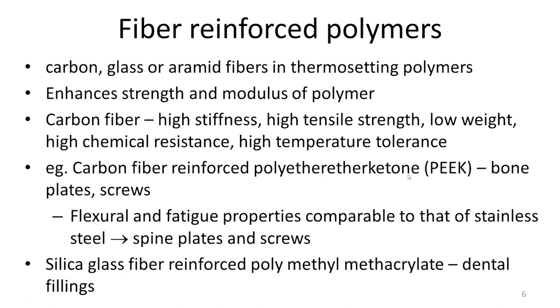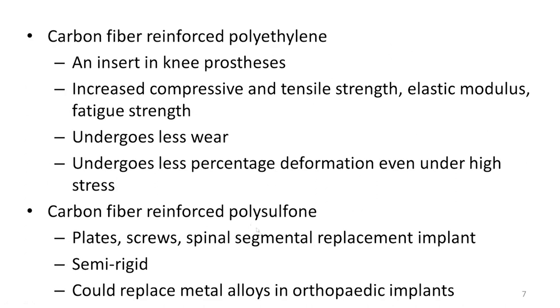Carbon reinforced polyether ether ketone is used for bone plate screws, with flexural and fatigue properties comparable to stainless steel, and is also used in spine plates and screws — while being much lighter. Silica glass fiber reinforced PMMA is used in dental fillings, where the fiber gives toughness. Carbon reinforced polyethylene is used in knee prostheses, where there is a lot of attrition, bending, and flexural stress.